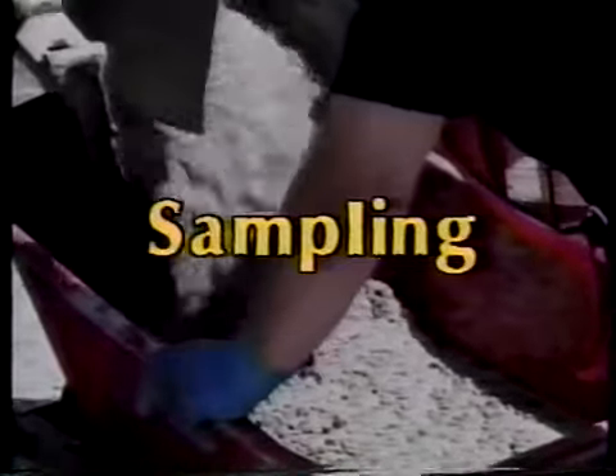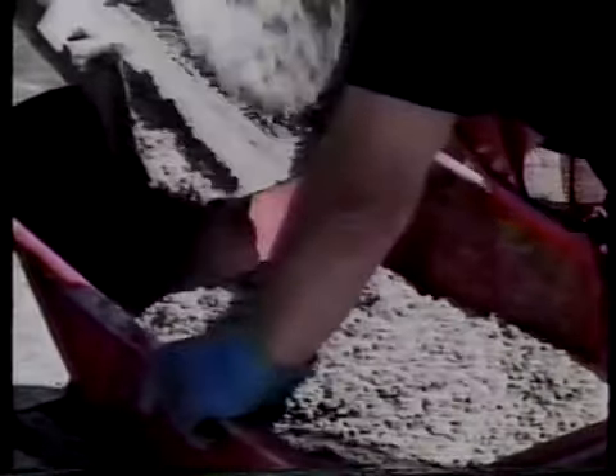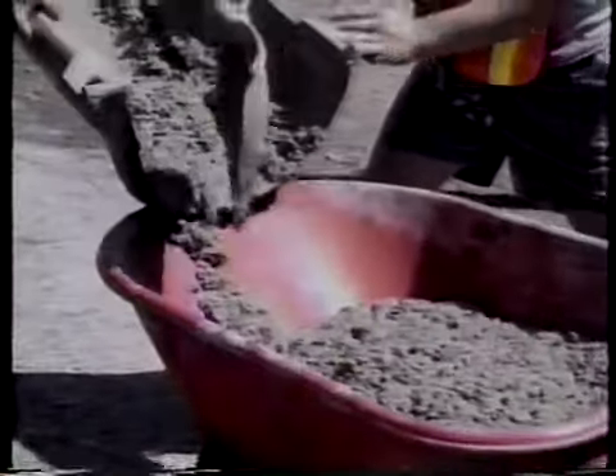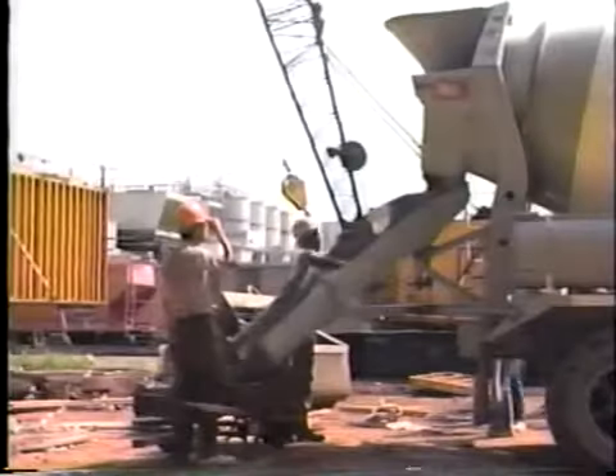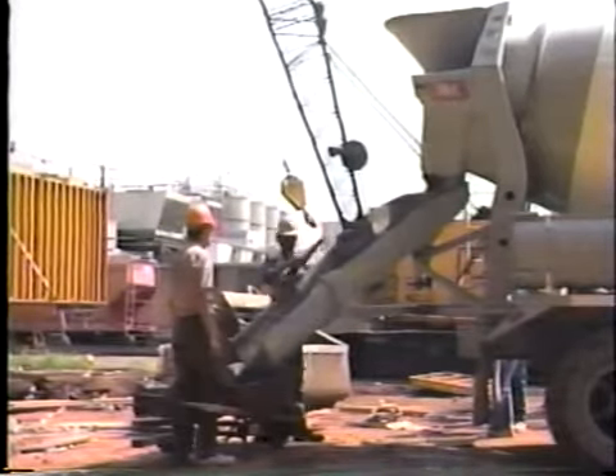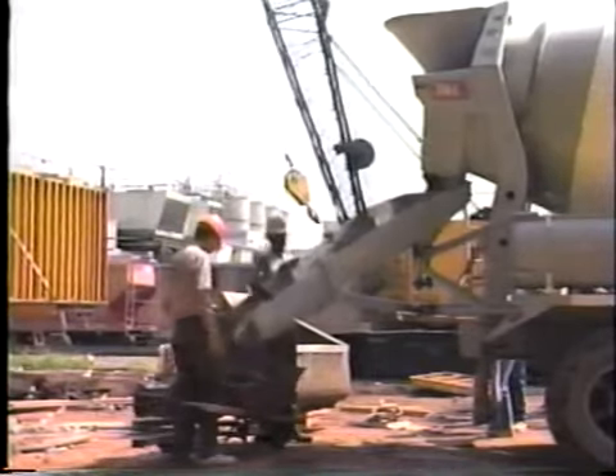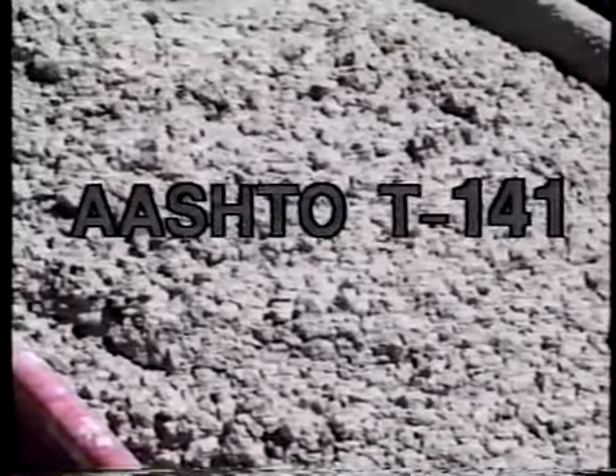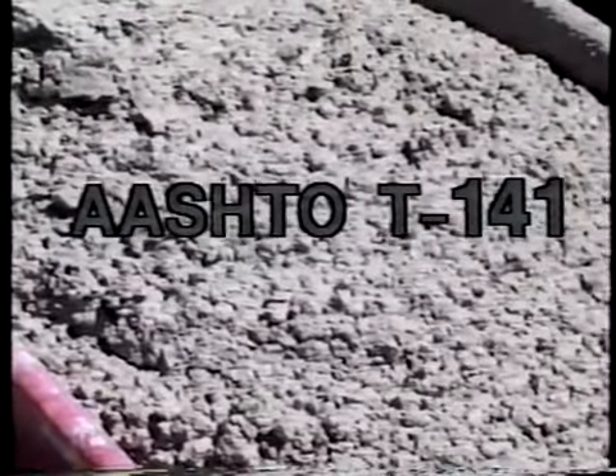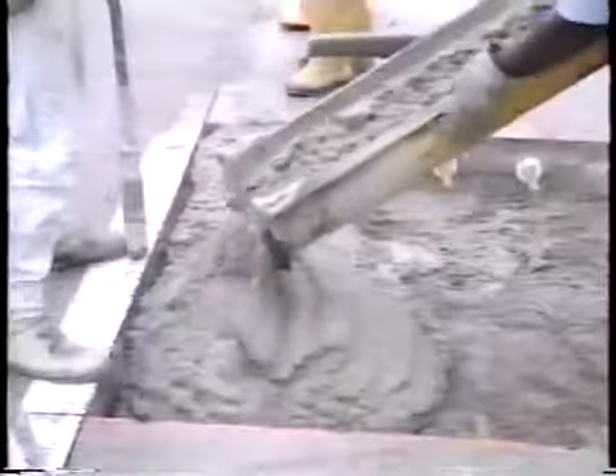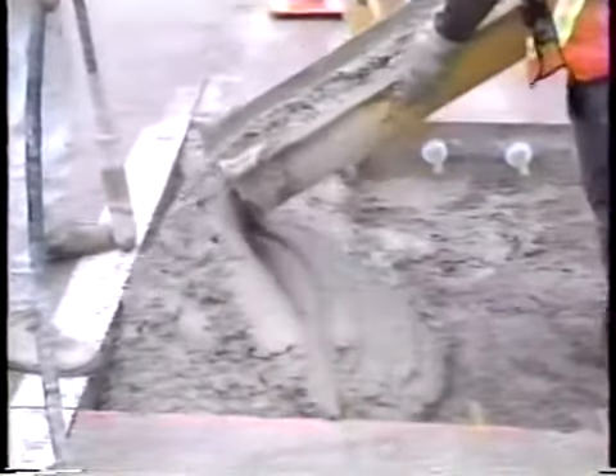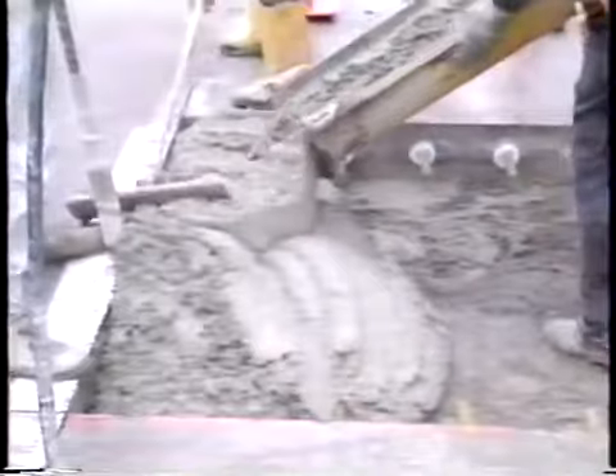Our first topic then is sampling. Before any of the tests can be performed, a sample of the concrete is needed, a representative sample. The concrete to be tested has to be typical of the entire truckload. Sampling should be done according to AASHTO designation T141. The basic rule is this: don't take the sample from the beginning or end of the discharge. Take it from the middle 1/3 of the discharge, but never from the first 2 cubic feet.